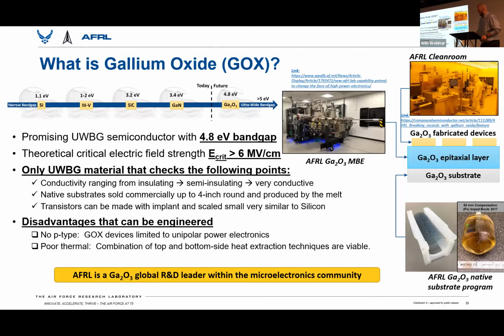So, Dr. Newton mentioned a little bit of this. What is gallium oxide? It's an ultra-wide bandgap semiconductor with a 4.8 eV band gap. That wide band gap is very interesting. It turns out it's the only ultra-wide bandgap material that you can dope from insulating to conductive, and it has native substrates sold commercially that are grown from the melt, a very cheap way to mass manufacture substrates. There are a couple of disadvantages. No P-type doping is available, something you can get in silicon or silicon carbide.